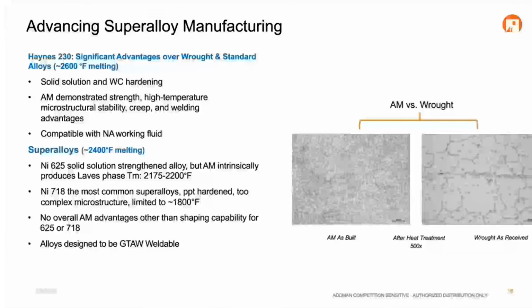The economies of scale make it very affordable pricing for the powder with wide availability. But when we start looking at high temperature applications, because Inconel 718 is a gamma double prime strengthened alloy, it's susceptible to basically a cliff where properties fall off as a function of increasing temperature, because those strengthening phases dissolve back into solution at around 1800 degrees Fahrenheit.